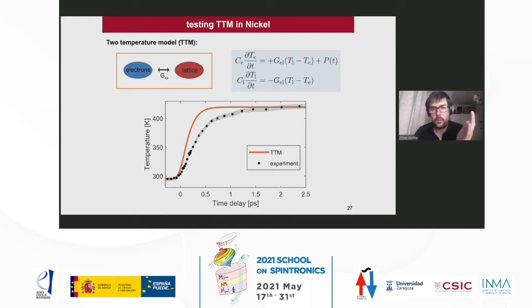This two-temperature model is too fast. The time scale of this electron-phonon relaxation is given by the electron-phonon coupling, but also by the heat capacity of the electrons in the equations. So what we did next is make the model a little bit more complex.